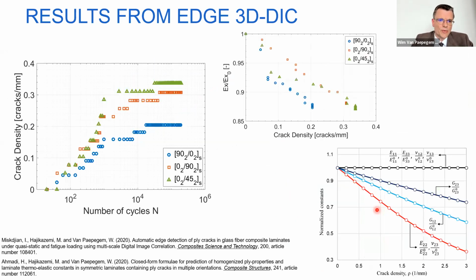This is very nice because if you now let your fatigue test run for a week and your system is there, you can measure day and night and get a crack density versus the number of cycles. So you see for different layups, you see the crack density growing over time. And also, like we know for fatigue, then at some point saturating to a certain value.